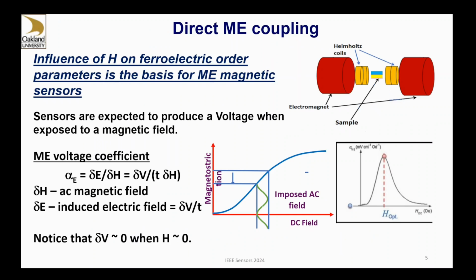So it could potentially be useful for detection of both AC and DC magnetic fields. The way it works for magnetic field sensors of AC fields, you need a bias field provided by either an electromagnet or a permanent magnet. Then you superimpose the AC field that you would like to detect. There is magnetostriction versus bias field, and when you superimpose the AC field, there is AC magnetostriction leading to the voltage response. This is what we measure in the experiment. As you see here, for very low bias field, there is very little magnetostriction. So it starts out at zero and then it peaks when the slope is maximum. This response essentially tracks the slope of the magnetostriction versus DC field.